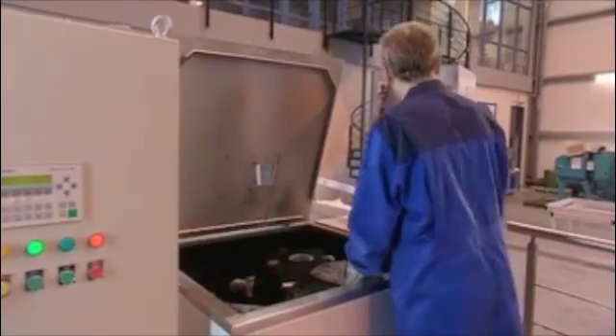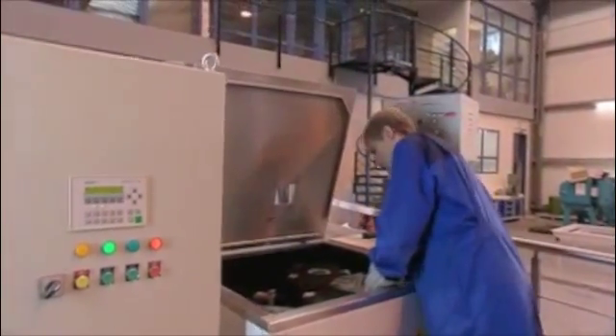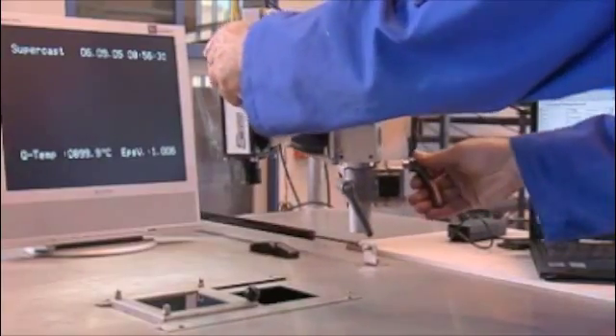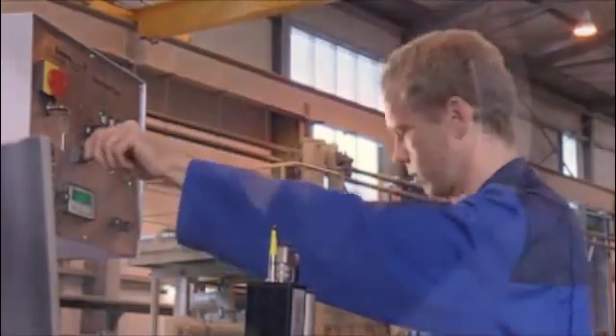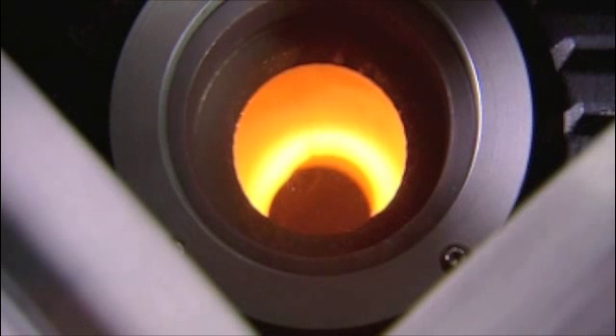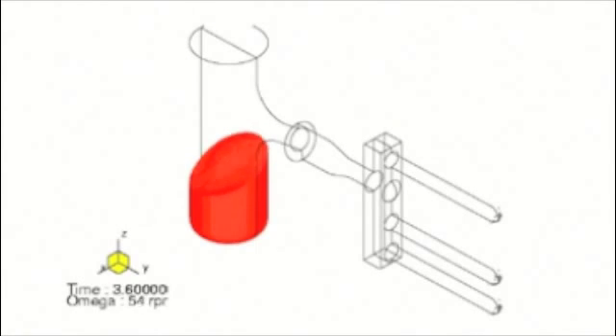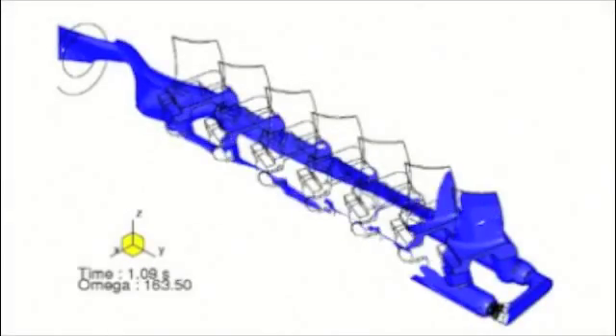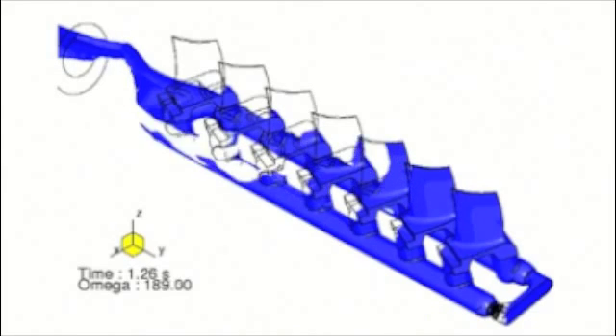The vacuum chamber is then sealed and the required melt and casting environment — a vacuum — is reached. The alloy in the crucible is melted in a magnetic induction field and its temperature increased to the casting temperature, which is over 1600 degrees Celsius. The centrifugal process can now be started and the liquid metal shoots into the mould shell. The high full-pressure level, in particular in the feeders, is maintained by re-acceleration until the casting completely solidifies.